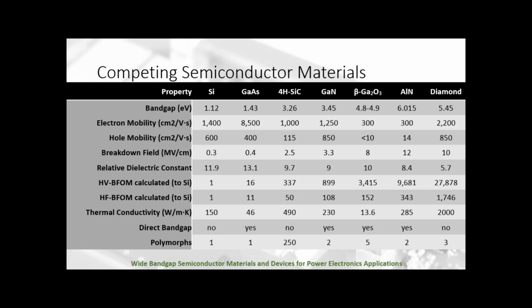And then as Professor Baliga himself told me, these numbers don't mean anything, or they mean way less if they're not measured on the same piece of material. So you can find yourself a lightly doped piece of gallium arsenide with a real high electron mobility, and it presumably has a reasonable thermal conductivity, but it might have trouble in one of the other categories, and it doesn't have any holes, so how are you going to get a hole mobility? So you really got to make these measurements on the same piece of material.